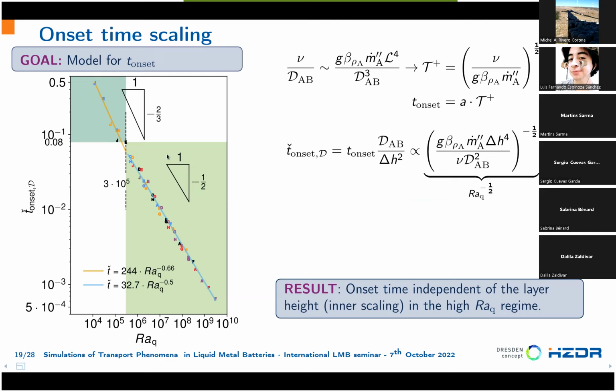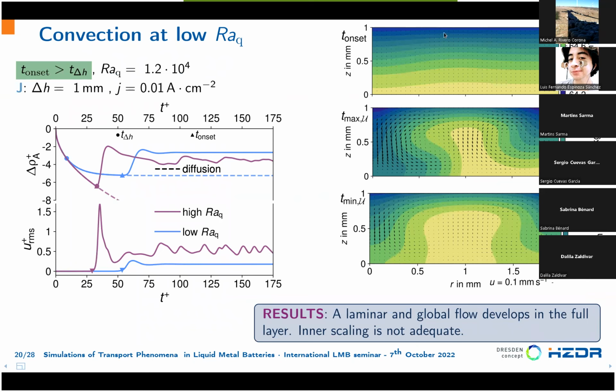Now we study what happens in the low Rayleigh number regime. In the low Rayleigh number regime, convection starts in the full layer. It's characterized by very large structures that are relatively laminar, I would say. The blue line is the low Rayleigh number, and we see that we don't observe any oscillation in the velocity, compared with the high Rayleigh number case. And the inner scaling is no longer adequate to describe this low Rayleigh number regime.